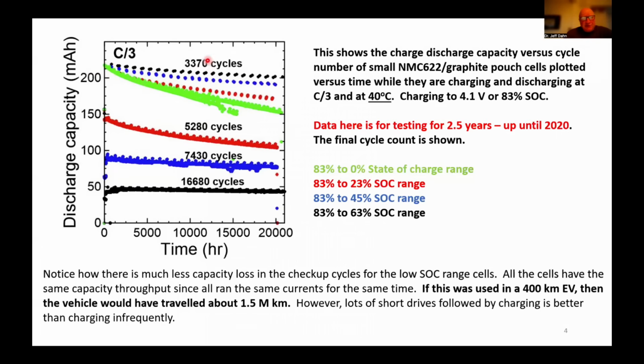And it's accumulated 3,370 cycles over this roughly 2.5 years. And this is all happening at a high elevated temperature, 40 degrees centigrade, where batteries degrade faster than they do at room temperature. And then the red is a cell that's undergoing discharge only to 23% state of charge, and the blue to 45%, and the black is just a 20% SOC range.